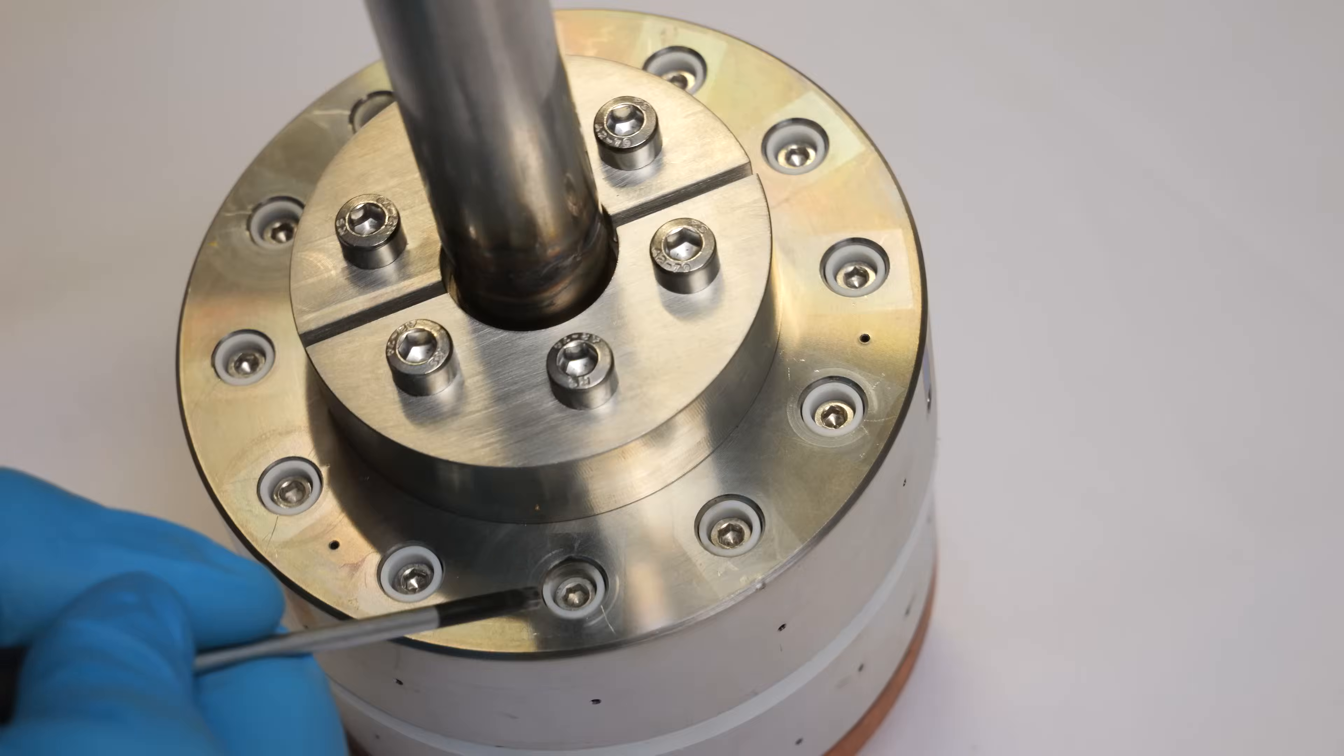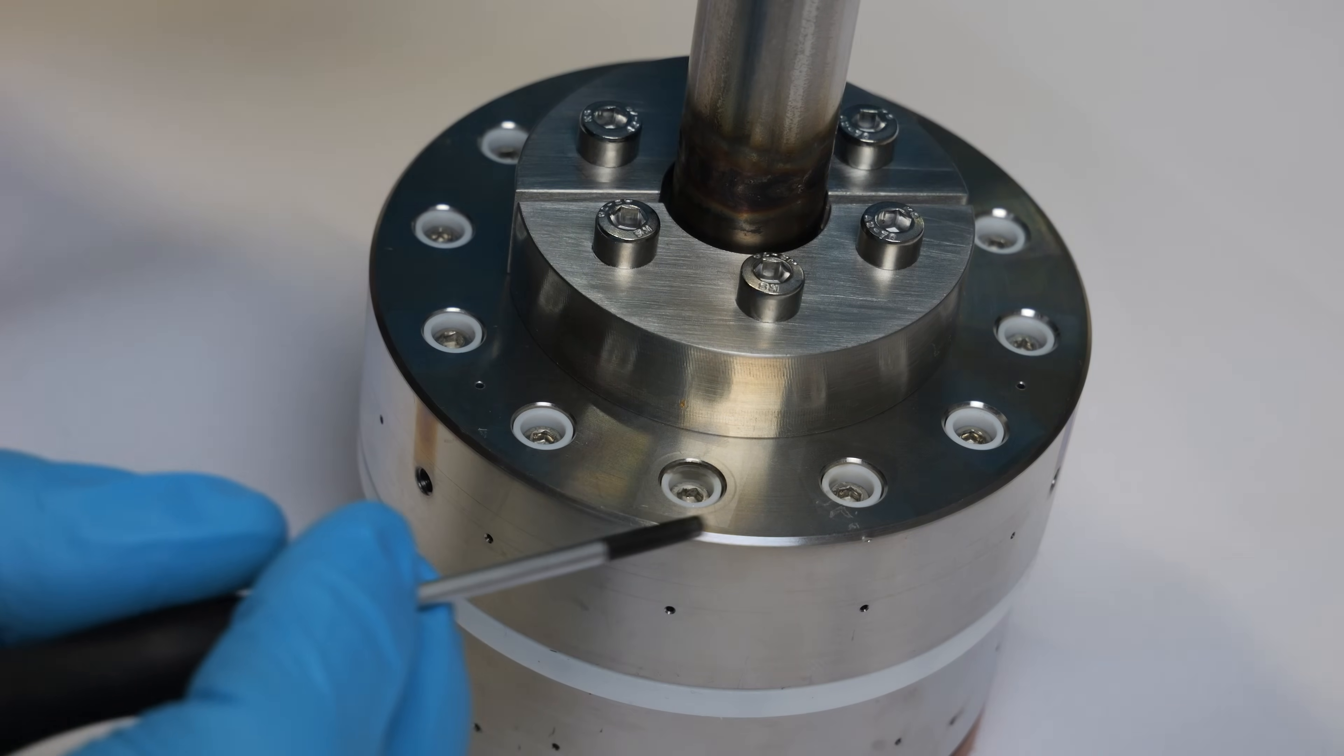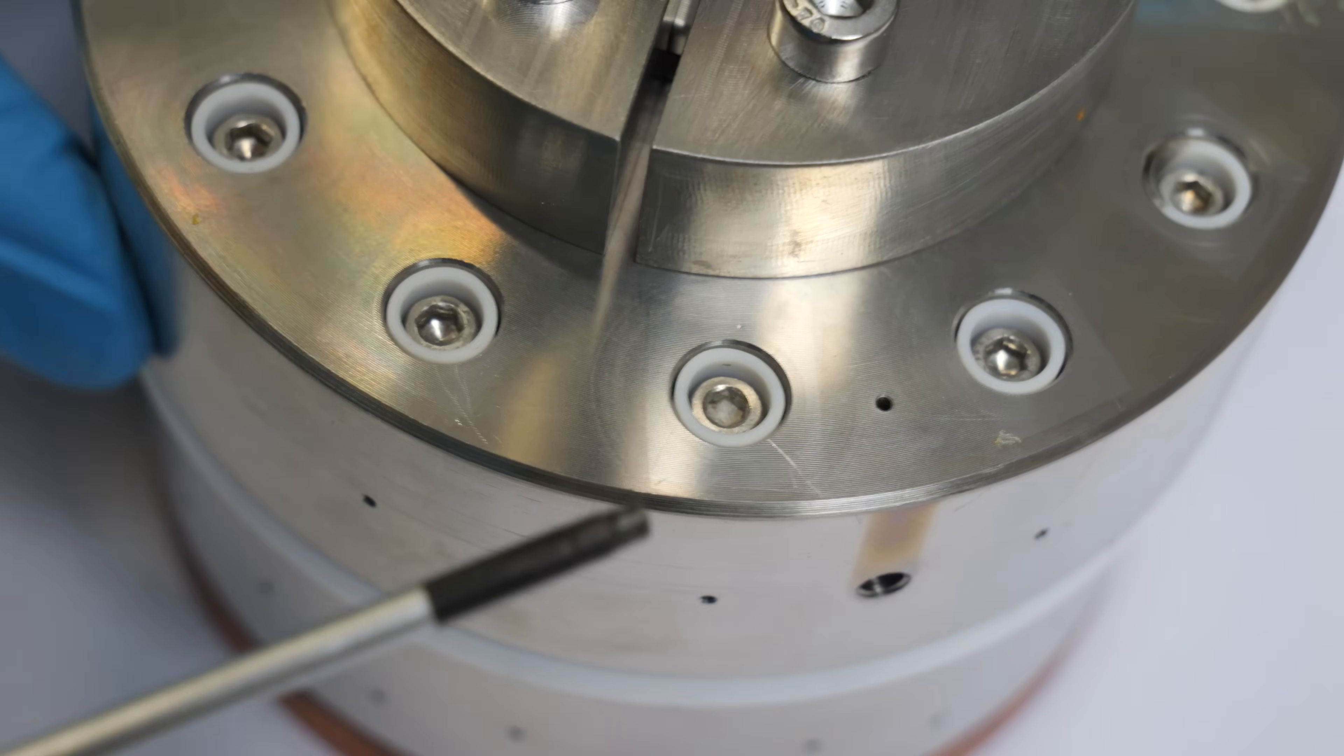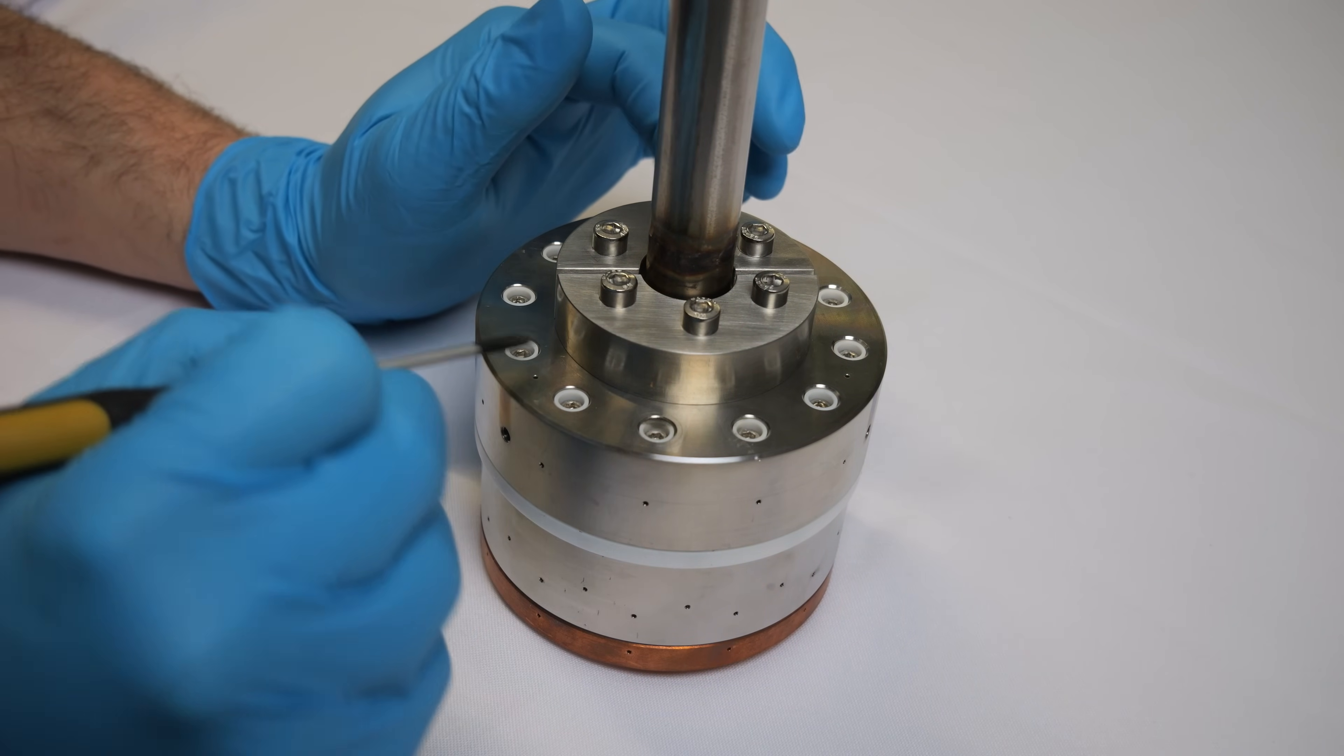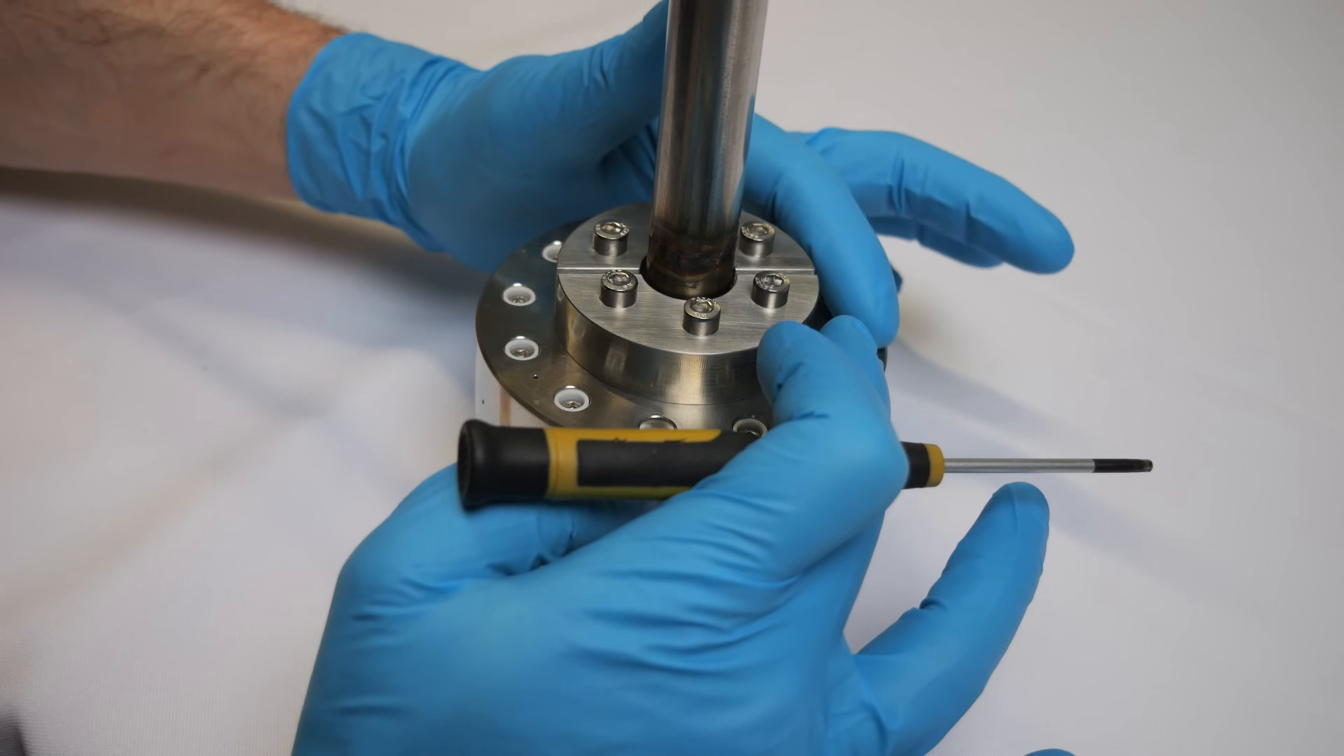The problem is that the distance between these screws at the bottom part is not very far and as you can see by the charring of the teflon right here at this screw and also right here. So a good upgrade for a future version would be some kind of insulation at the bottom of these screws. Maybe a secondary shield which just goes at the bottom right here.